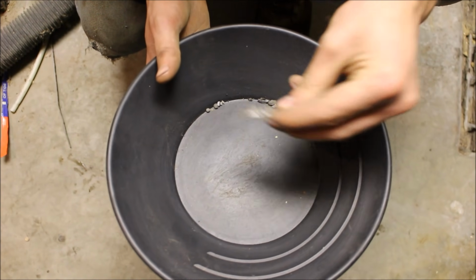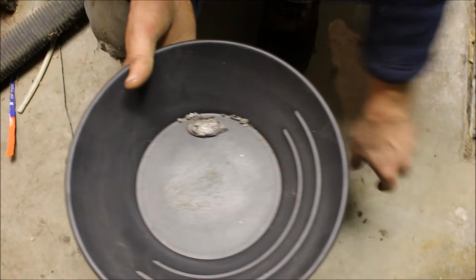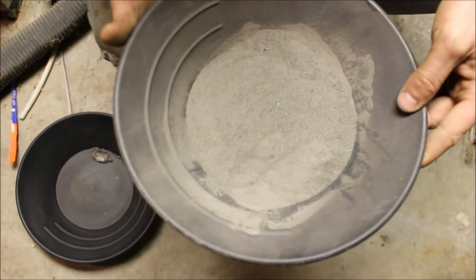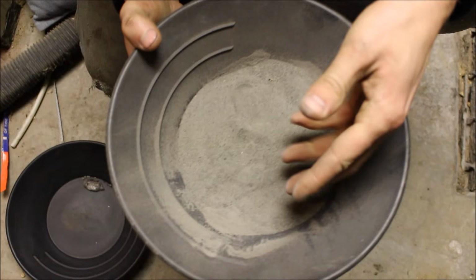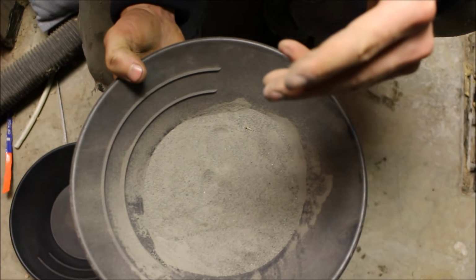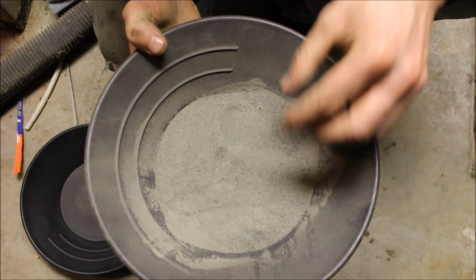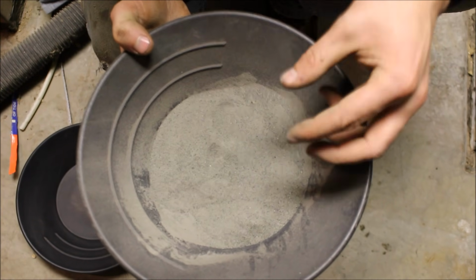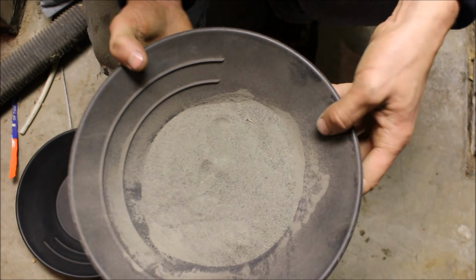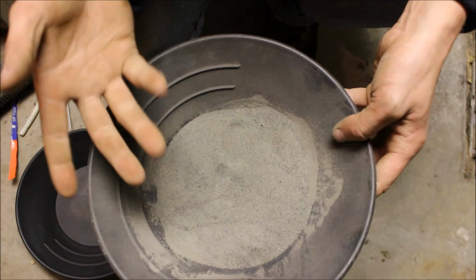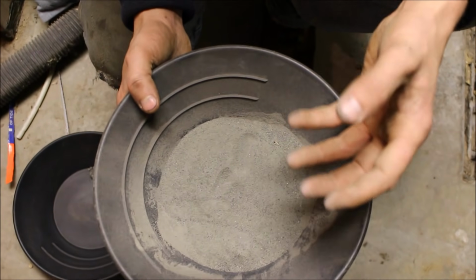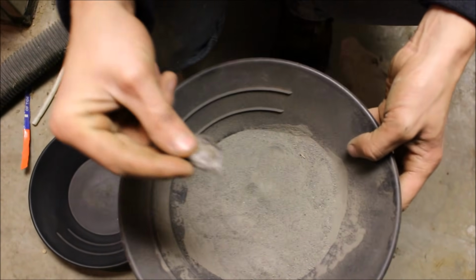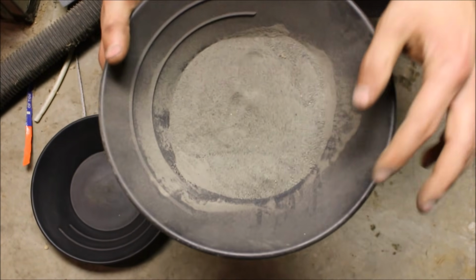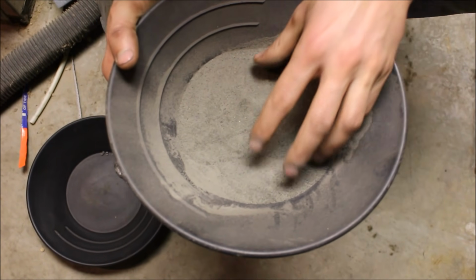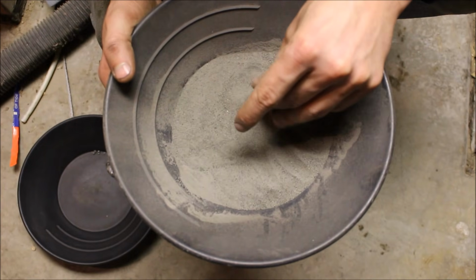Alright, so here's the big pieces of lead that I was able to pick out by hand. There's also a lot of little tiny pieces of lead, which of course contain gold, because what I was doing is using the lead to dissolve the gold particles, because the furnace wasn't getting hot enough. The lead lowered the melting point of the gold basically, so that it would actually turn into a liquid and form into solid beads. But I wasn't able to keep it hot enough for long enough, so not all the beads collected at the bottom of the crucible.